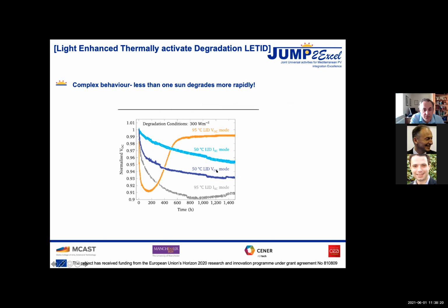So these are under open circuit and short circuit conditions. You can see that at 95 degrees C, so very high temperature, well, for terrestrial standards, the whole process is over and done with in 600 hours. Whereas at 50 degrees C, which is a more temperate climate, perhaps, it's slower. And so after 1400 hours, it's still degraded. And this takes a similar amount of time to recover. So very long periods, years, potentially. So yeah, that's the process.